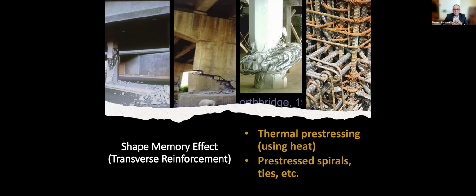The process is very simple. We have pre-strained wires or bar made of SMA. It's delivered already to the site in the pre-strained condition. You form it as a spiral, you put it in the form, and you cast the concrete. When the concrete sets, you now can activate it by subjecting it to temperature. It will attempt to shrink, it will try to squeeze the concrete, and that squeezing effect, we call this lateral pre-stressing, transverse pre-stressing, or sometimes we refer to it as active confinement. So that is the unique thing about these materials.